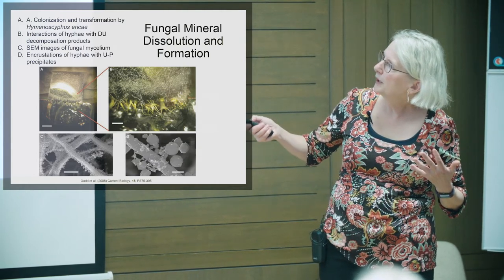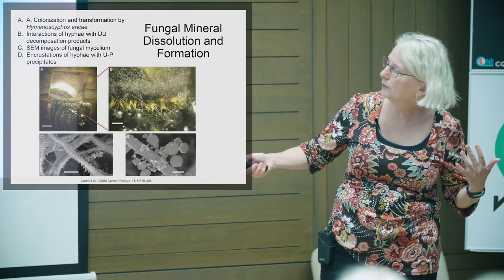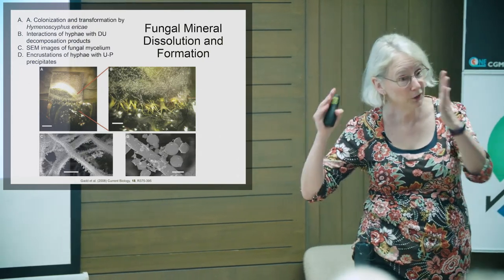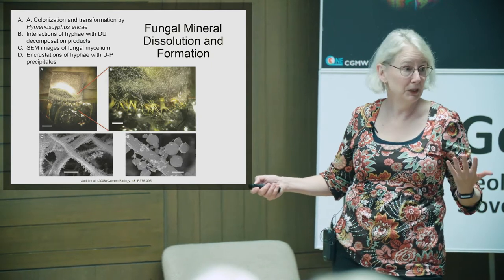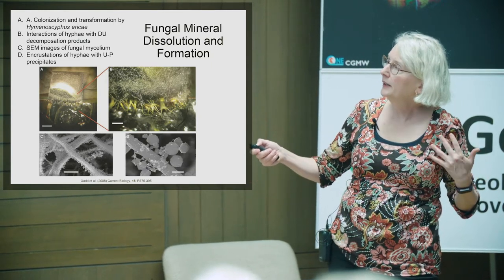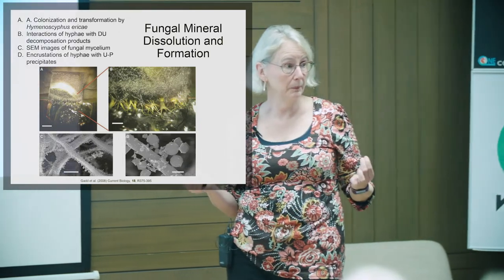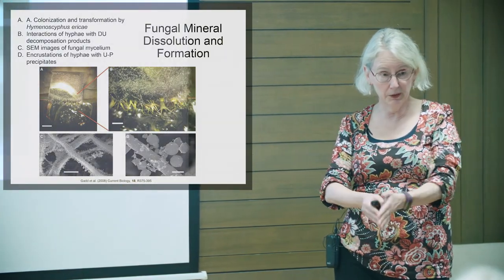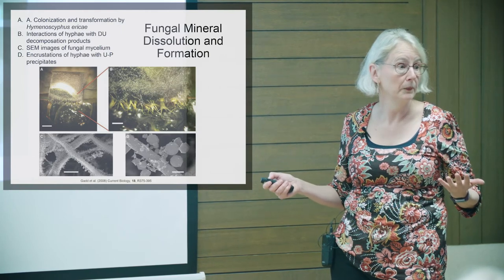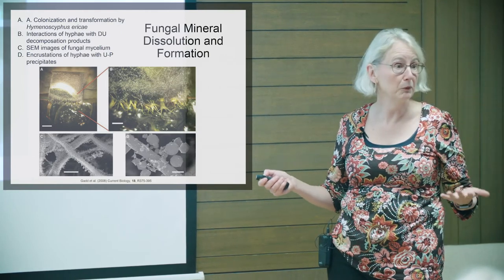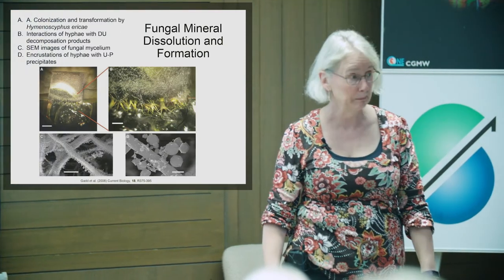And the fungi start to put hyphae down on the surface of the depleted uranium. Here's an enlargement of that. And you can see the fungi now going into the depleted uranium. But in this case, not only did they dissolve the depleted uranium, they also caused precipitation of these minerals. So you can see they're lovely platelets. They're hexagonal platelets, actually. And they're formed of uranium phosphate. That's a really good thing, because uranium phosphate is incredibly insoluble. Phosphates are one of the most insoluble types of minerals there are. So by these fungi making these minerals, that's locking away the uranium in a stable form. So although it's breaking it down, it's actually causing a type of remediation. And that's because the fungi likely are going for the uranium to change the oxidation state of the uranium.